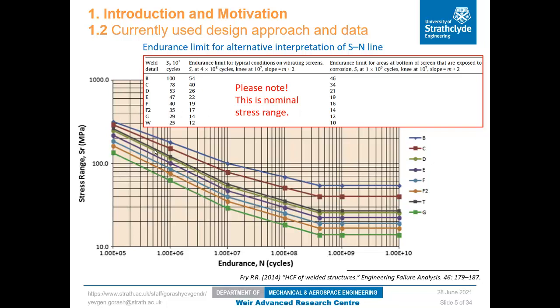When looking at these S-N curves closer, we can notice that they are extremely conservative because they guarantee 97% reliability. And looking, for example, at weld type W, we can see that in its corroded condition, the stress range is limited to 10 megapascal, so we are talking about a plus minus 5 megapascal operating range for this type of welded connection. And this is of course extremely conservative.